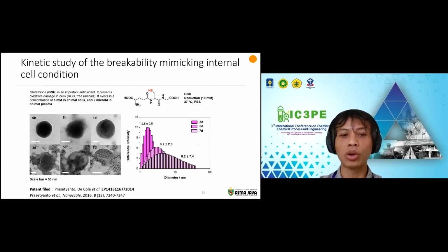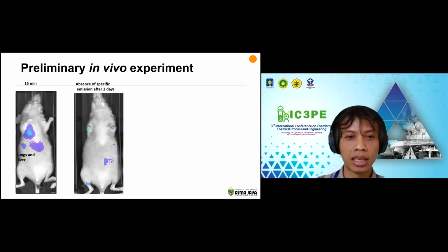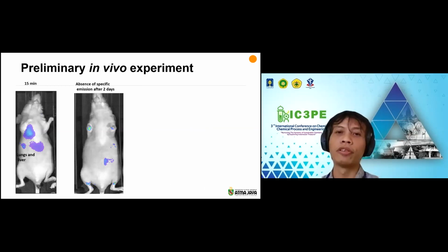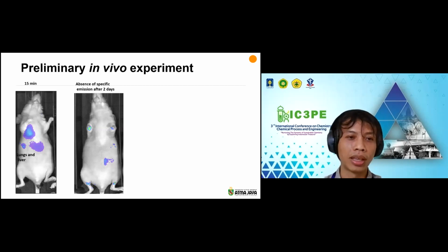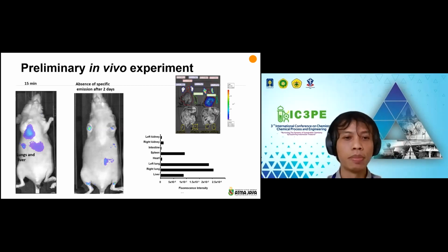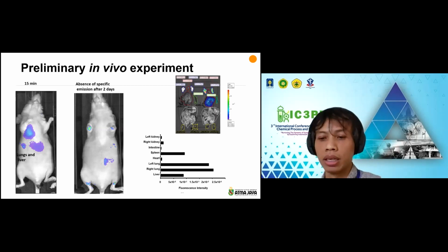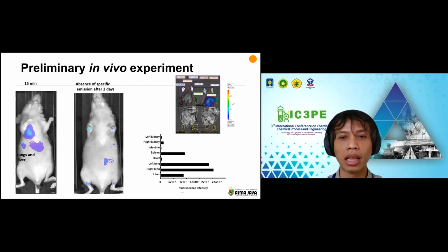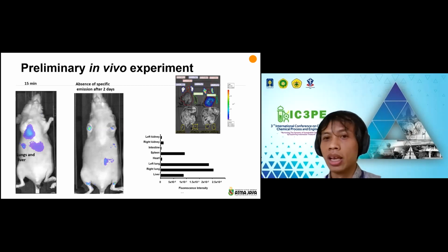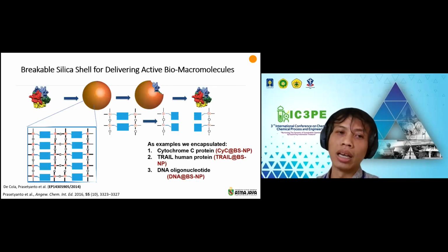This is the static condition. In the static condition, the particle will break apart in 7 days. And then we also did some preliminary in vivo experiment that after 2 days there is an absence of specific emission. It means all the particles we injected in the mice cleared out perfectly.